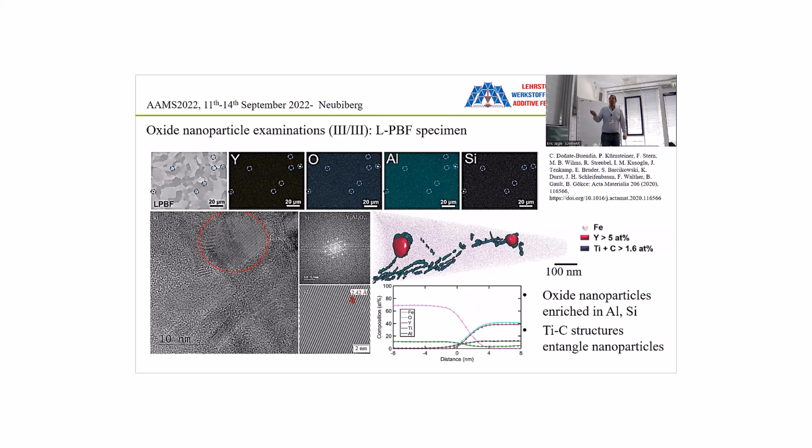And we also find here some titanium carbides, and they look very strange. They're not single carbides which are dispersed in your matrix. So we think maybe this is not correct, this is just an idea. We see here some dislocations where these carbides are sitting on, and so we can actually observe some dislocation interaction with our oxide particles, which is exactly what we're looking for.